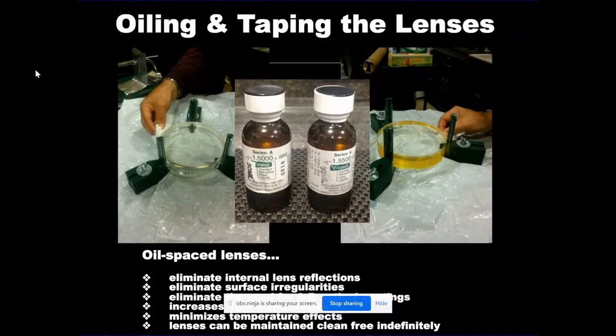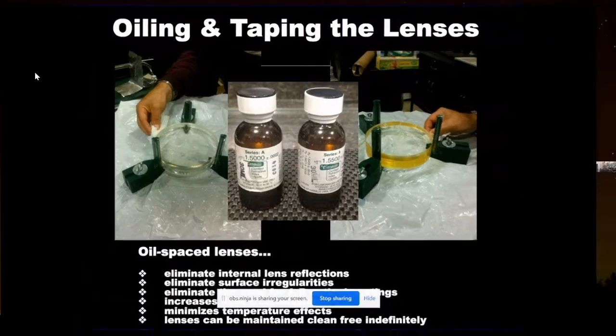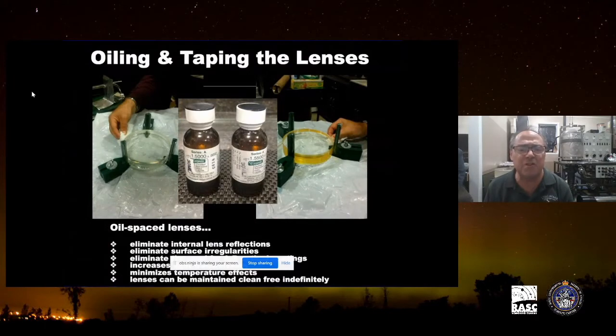Some of you have high-end refractors such as the apochromatics that use oils as well as coatings, or a combination of the two. And this is how the oiling works. My apochromatic refractor is an oil space triplet. There's no airspace, but there are 3 different lenses. What's nice about these oilings is that they eliminate a lot of problems. First of all, they eliminate all the internal lens reflections. They eliminate any irregularities, so the internal surfaces don't need to be figured. They just need to be more or less polished. It's not affected by temperatures, and these can be maintained clean indefinitely.